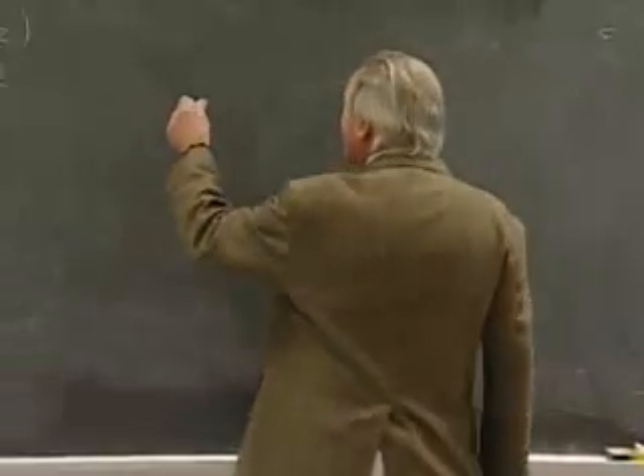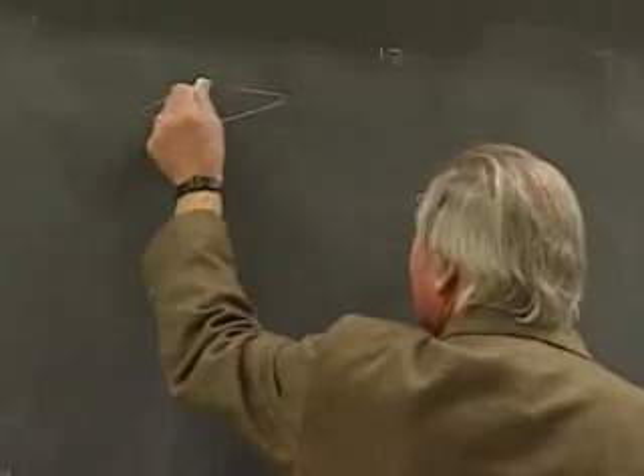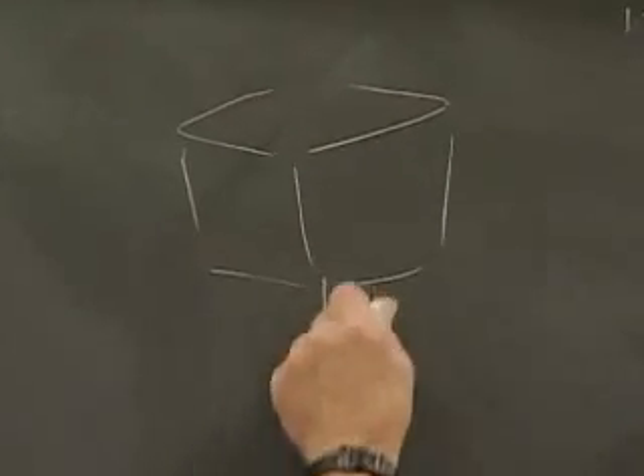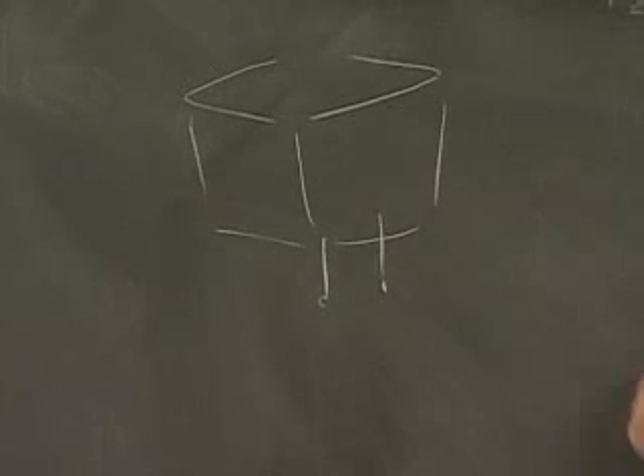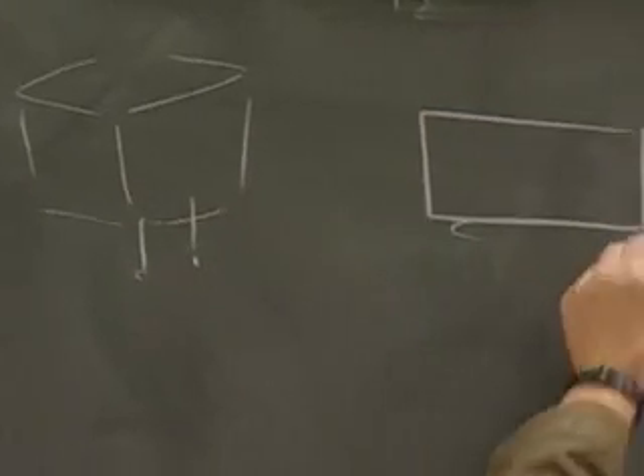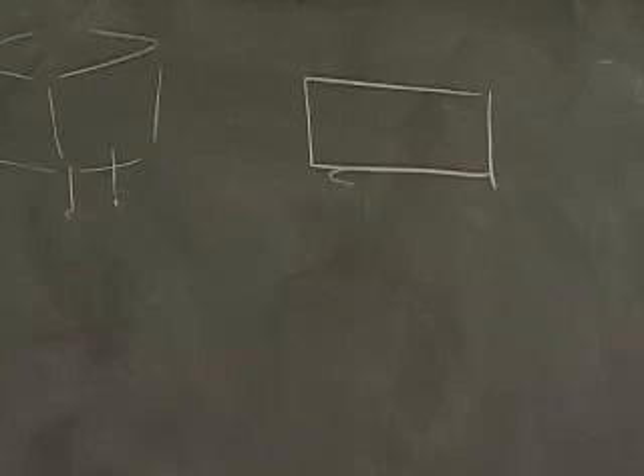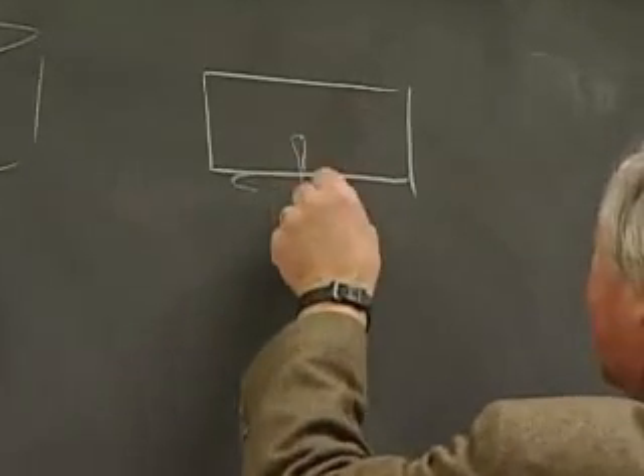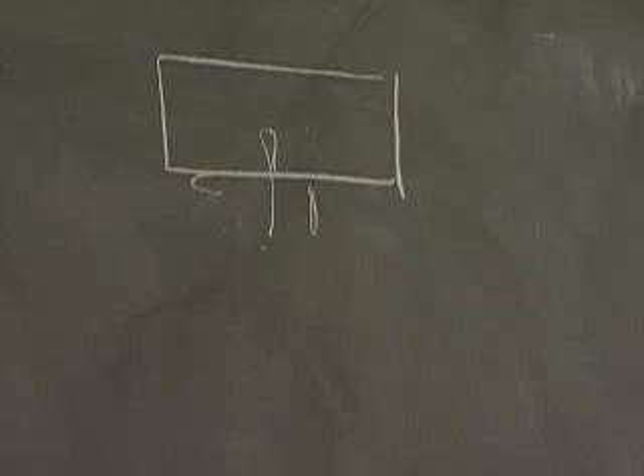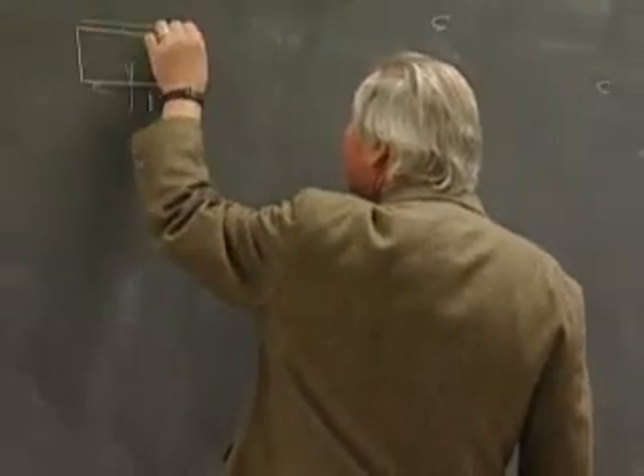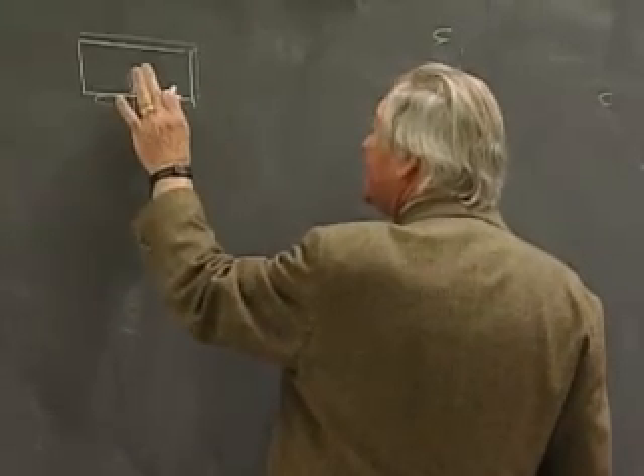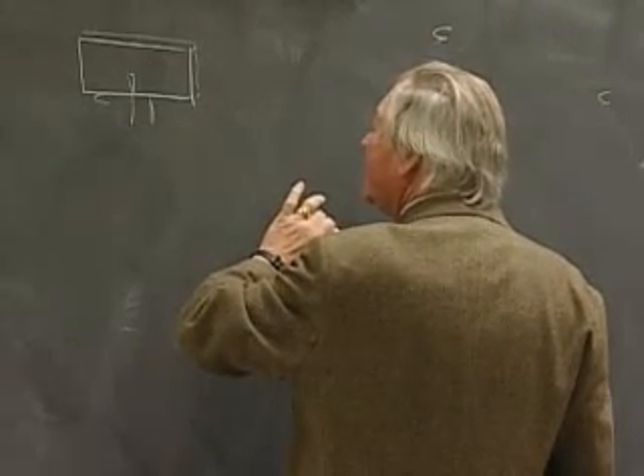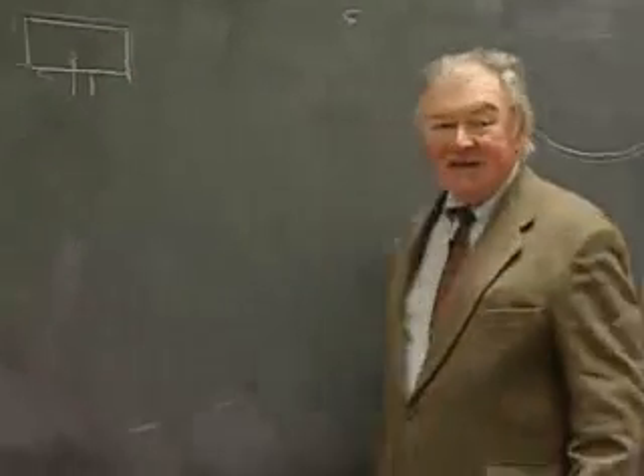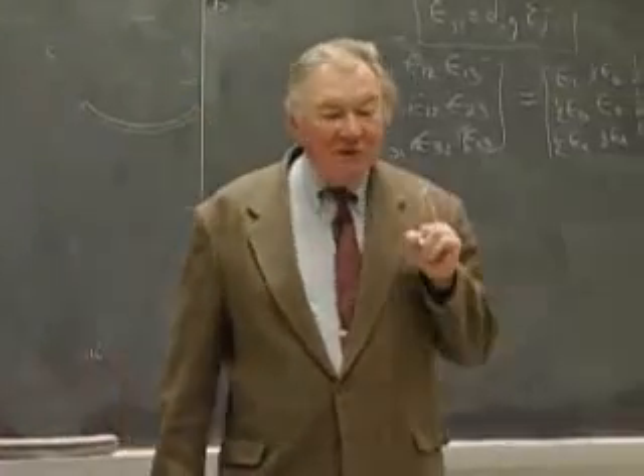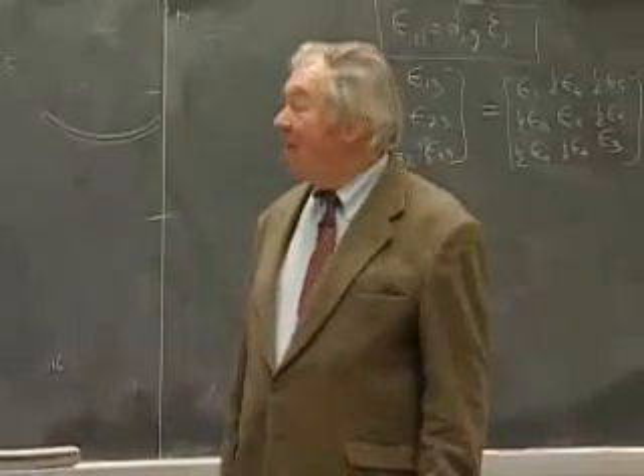The so-called crystal was exactly that. It was a little black box that looked almost like a transistor, and there were two leads coming out of it. If you ever got curious and broke this thing open, what you found was a nice wafer of quartz, and on the wafer of quartz, brazed onto it, were two wires, and that's all there was in the box. The crystal really was a crystal, and the crystals had been very precisely ground to thicknesses such that when a field caused these wafers to hit a resonance, that resonance would be at exactly a particular frequency, and that was the frequency of that channel.